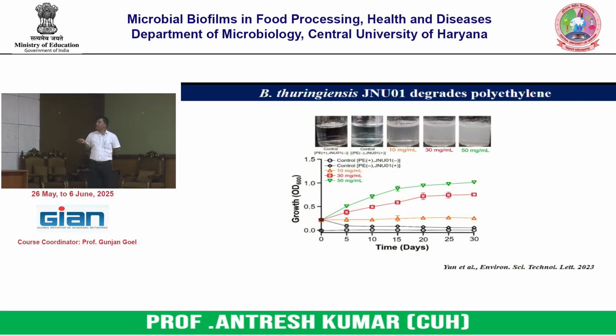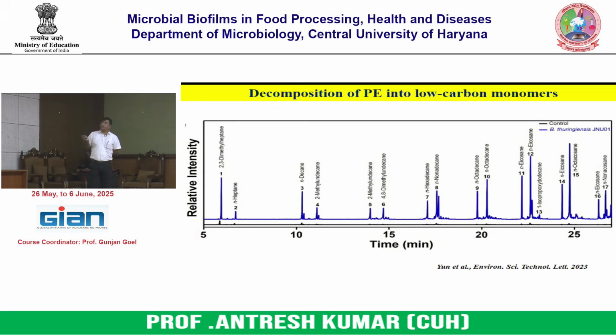So what they did was grow this bacterium in different concentrations of polyethylene, and if you look at the growth, as the concentration of the substrate increases, more growth is observed. That means the Bacillus thuringiensis JNU1 strain tends to degrade and utilize the polyethylene for growth. As a result, the growth is increasing. You can easily visualize the turbidity of the bacteria grown in the agar medium, where the polyethylene is present in the agar. This particular strain, JNU1, can also decompose the polyethylene into low-carbon monomers. This is the GC-mass spectrum diagram, where you can see the different small molecules decomposed with the treatment of Bacillus thuringiensis JNU1, showing that the polyethylene can be degraded into different types of small carbon molecules.